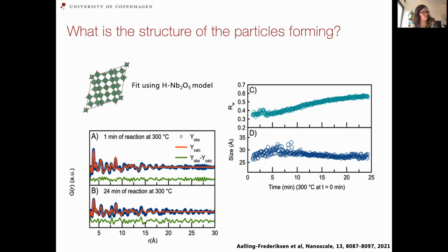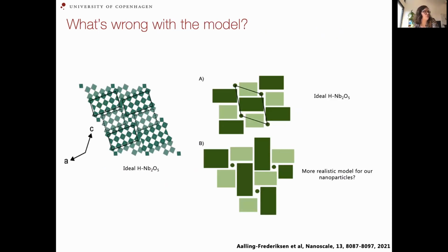When we were looking at this fit, what was not fitting was the amount of these edge-sharing octahedra that appear in the structure. In the experimental data, we saw we needed more edge sharing than corner sharing, more than we had in this material. So we were looking at different structures. Here we have the ideal H-Nb2O5 material that is known from the literature. But what we found was that maybe what was missing was that the sizes of these domains of this rhenium oxide structure were not really corresponding to what we saw in our nanoparticles.